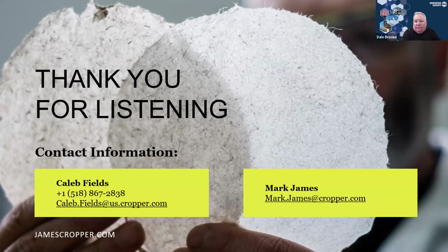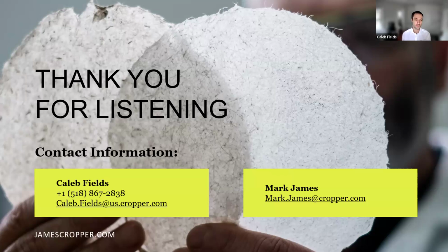So does the EMI shielding non-woven on the battery boxes tear at high elongation areas like corners during molding? Yeah, so it's going to depend on the manufacturing method. We have materials that are developed for specific manufacturing methods. For instance, we've been working the last couple of years on a project to integrate our EMI shielding materials into the SMC process, and our solution allows the materials to flow in the SMC rather than tear, where typically a non-woven would tear. Other than that, it would come down to the specifics of the manufacturing process, but typically our materials are compatible with most manufacturing processes, and we rarely see issues like that.